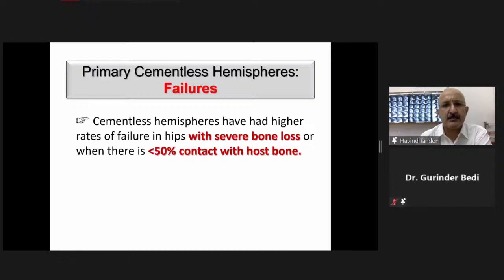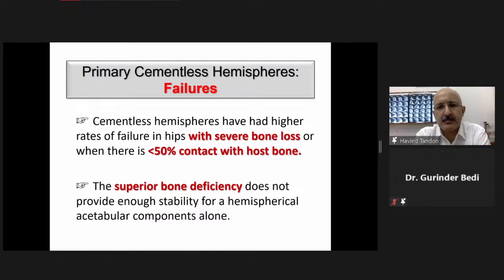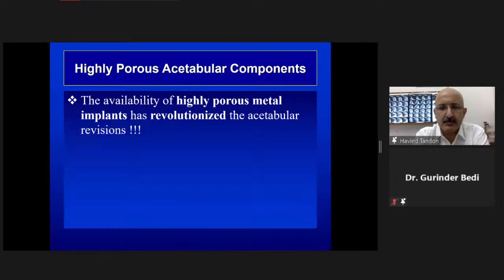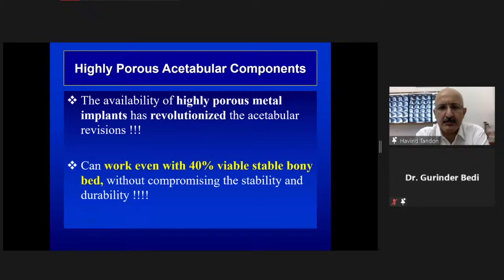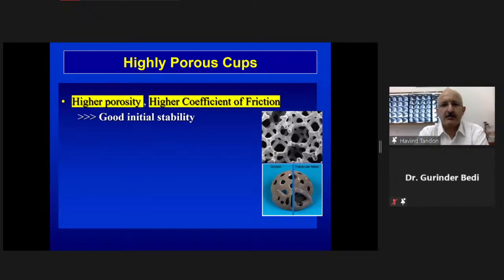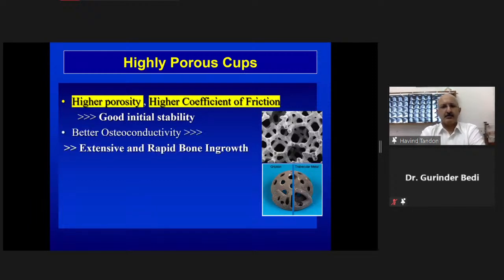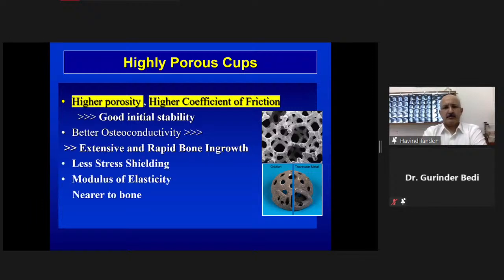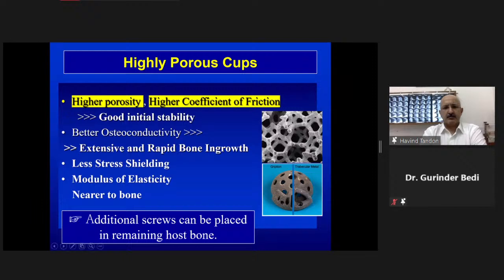Now, when will primary cementless hemispheres or shells fail? In cases of severe bone loss where you can't get 50% contact with host bone, or if there is significant superior bone deficiency not supporting the cementless shell. In such situations, highly porous acetabular components come to your rescue, which can work even with 40% viable stable bony bed. And they have higher porosity, higher coefficient of friction, so good initial stability. And all these properties have been spoken about by my previous speakers. And the best part is that you can put additional screws through these cups with a special drill bit in an area where the bone is strong in a revision scenario. That's very useful.